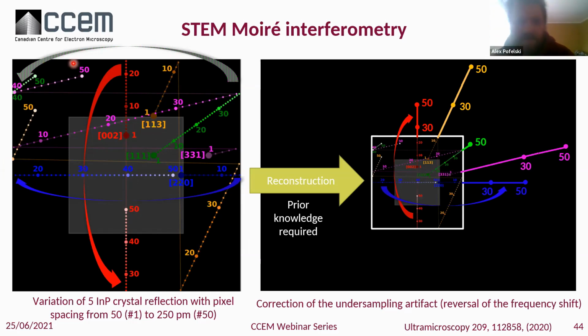This type of process is predictable, because this is the typical effect of sampling. So it is possible to reconstruct using prior knowledge. The reconstruction is very simple. All these elements that are shifted in one sense, you shift back to the original position. So you make an extension of the Fourier space and bring back all these elements, here, there, and you back to the area that is outside of the Fourier space, but that still should be there. So a little bit of prior knowledge is required, and this is what the processing is doing. The software is doing that for you on the condition you bring a little bit of input, and this is the complexity of the technique.